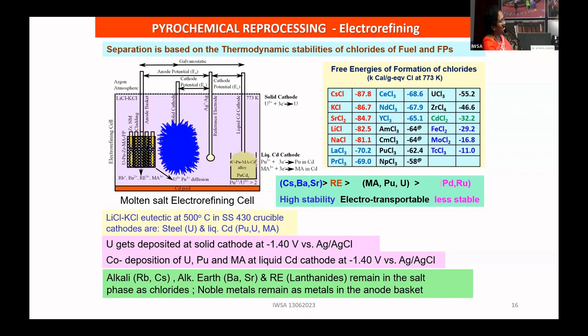Through electrochemistry, by playing with the potential, you can deposit uranium on the solid cathode. The remaining uranium, plutonium, and all the minor actinides can be electrochemically deposited in the liquid cadmium cathode, and that can be removed. As I told you, the highly stable alkali and alkaline earth chlorides will remain in the molten salt. Minor actinides and plutonium, which are electro-transportable, are taken into the cadmium cathode, which can be recovered. Uranium alone, by controlling the potential, you can deposit at the solid cathode, which is shown as the blue material there. And the noble metals remain as noble metals in the anode basket, which can be recovered.